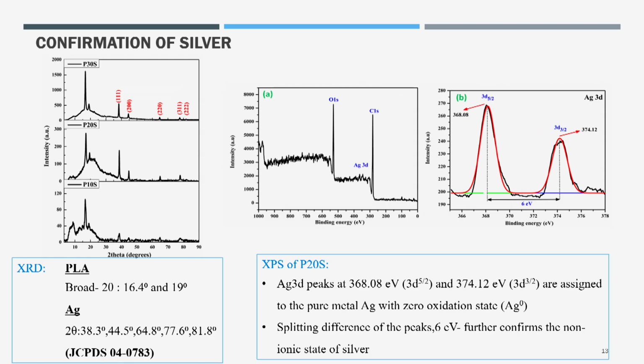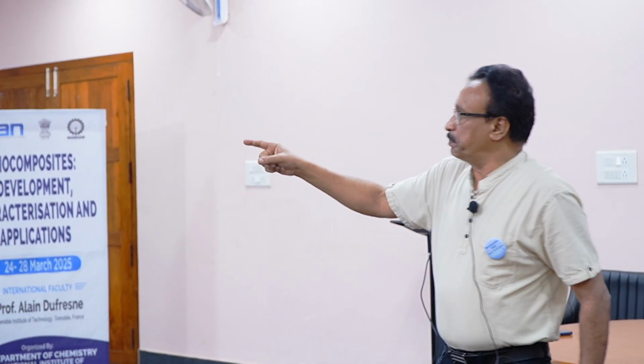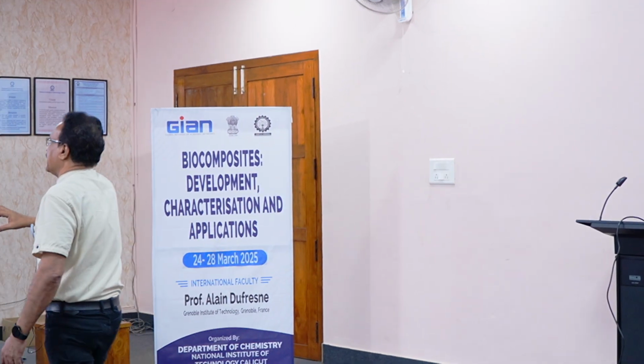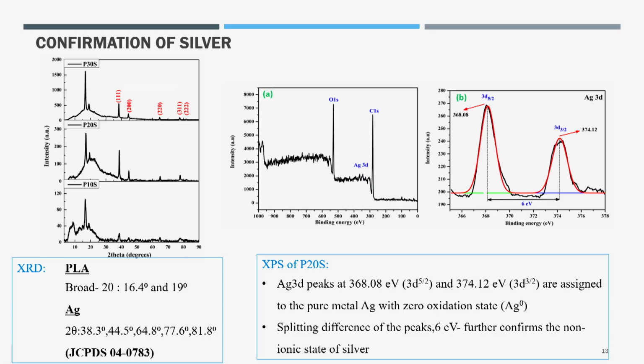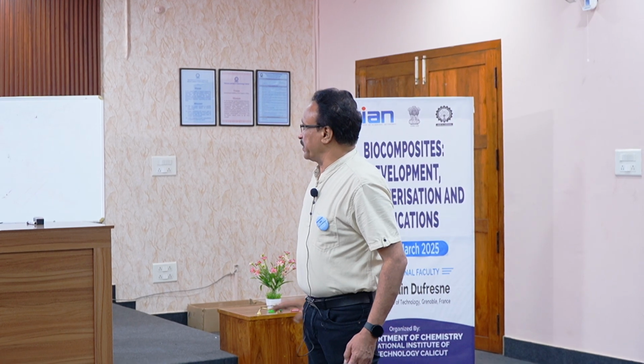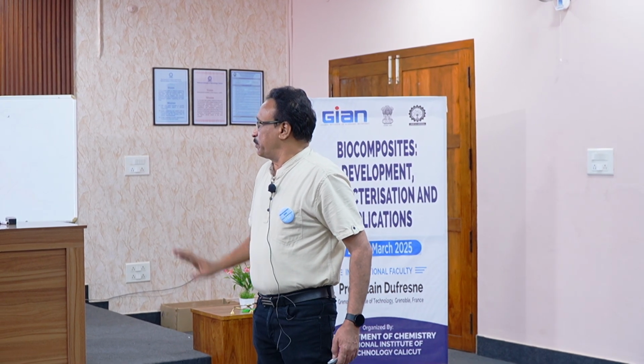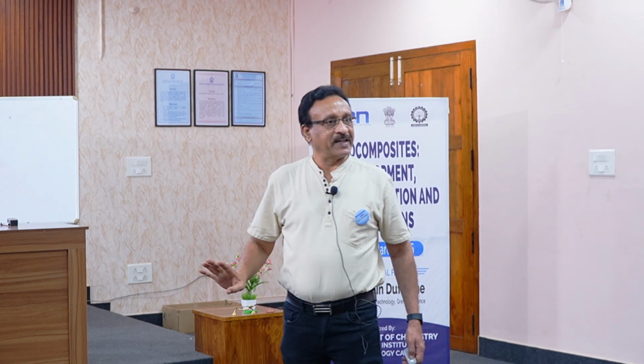The left hand side result is called X-ray. Exactly. How did you know that it is X-ray? Intensity versus 2 theta is plotted. The moment you see that, you should know what spectrum it is. Since the graph contains intensity on the y-axis and 2 theta on the x-axis, it's an X-ray. You can see that PLA should have 2 theta values of 16.4 and 19 degrees, and silver should have 2 theta values of 38.3, 44.5, and 64.8.